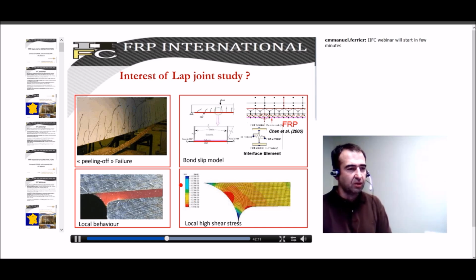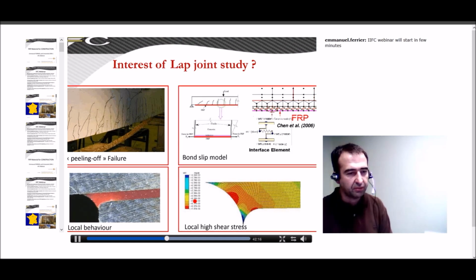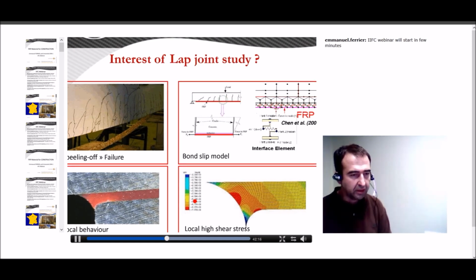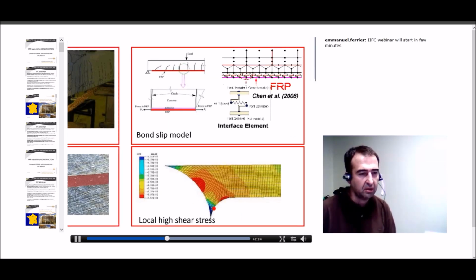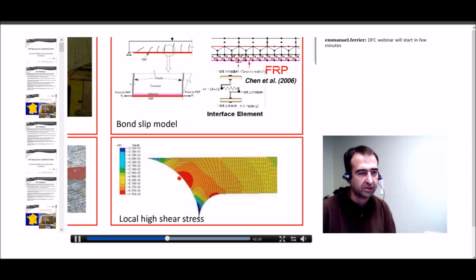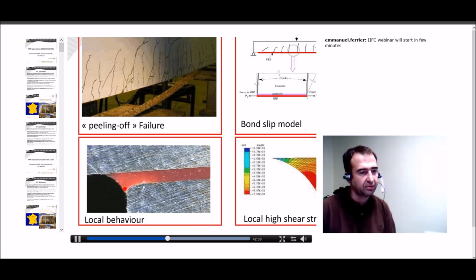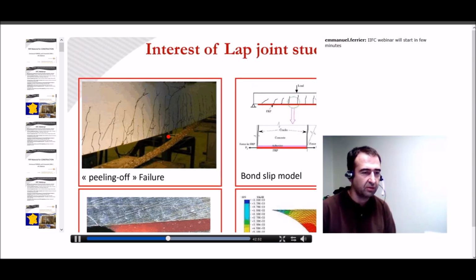About this, there has been a lot of development. We are aware, if we look at this, for example, which comes from the aeronautic industry and mechanical research, that at the end of the lap joint we have some important stress, essentially because we have two different materials bonded together with different mechanical properties. You have such an image showing that shear is the main issue and the main problem. And this shear, generally in the field of reinforced concrete beams, is known to cause full delamination or peeling off of the structures.